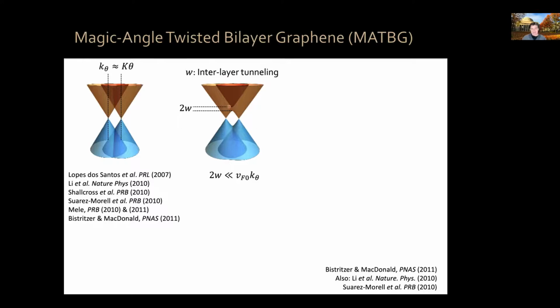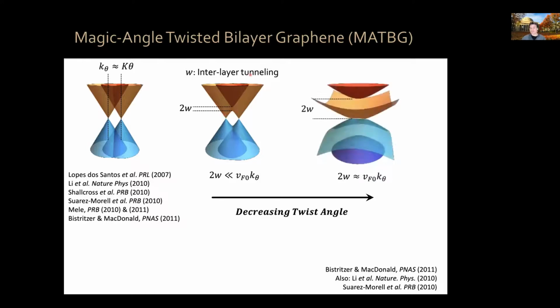And this interlayer tunneling leads to this band repulsion, in particular to this band that gets closer to, lowers its energy. This is the situation when the interlayer tunneling is much smaller than the energy of that crossing point, which is given by this formula. Now, as you decrease the twist angle, this lower band here gets pushed down further and further in energy until you reach 0. When you reach 0, this is something known as a flat band condition.